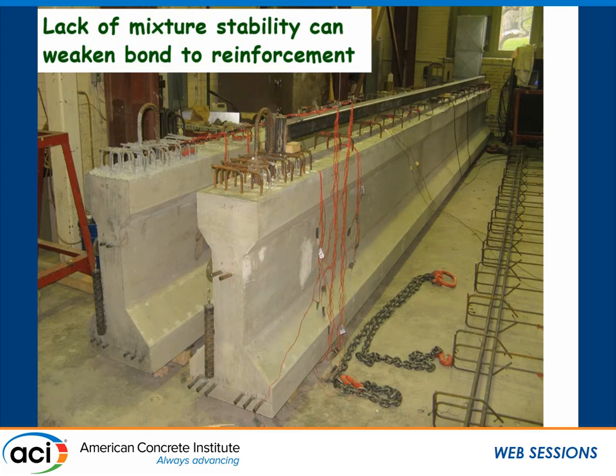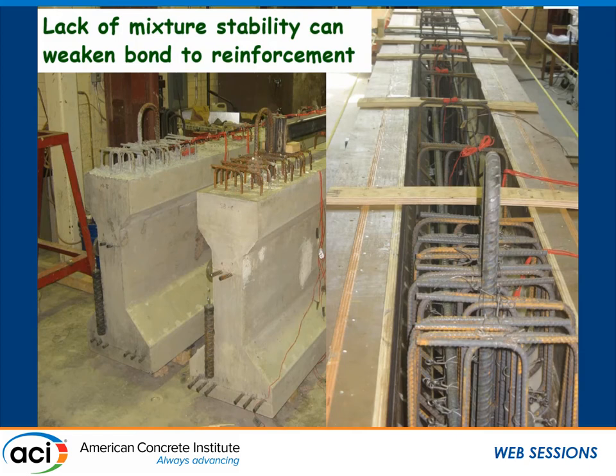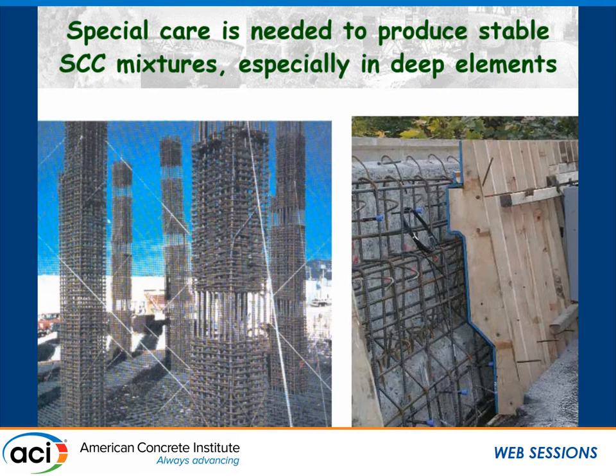So bond is very important, especially if you're dealing with pre-stressed concrete elements. These are I-shaped girders, and they have a certain height, and you have pre-stressing tendons, you have rebars, and you want to ensure that the bond is very, very high between the SCC and the embedded reinforcement. And if you are using SCC for vertical construction, high-rise buildings, shear walls, columns, again, bond between the concrete and the reinforcing steel determines the performance of the concrete. In this case, for repair, bond also is very important, especially when you are trying to develop concrete that has good resistance to cracking and good durability.